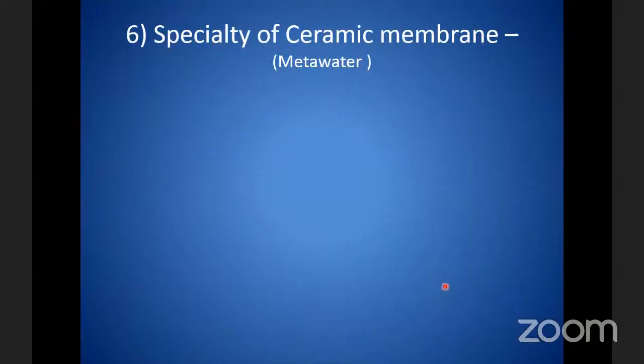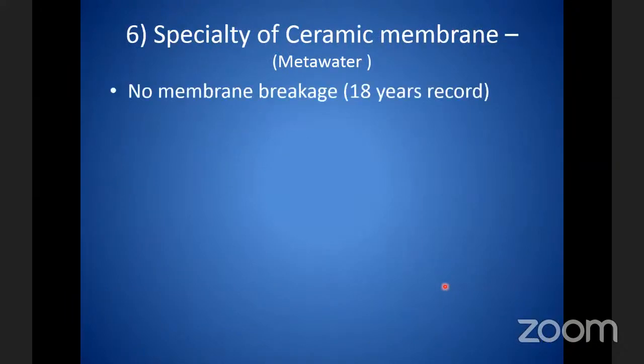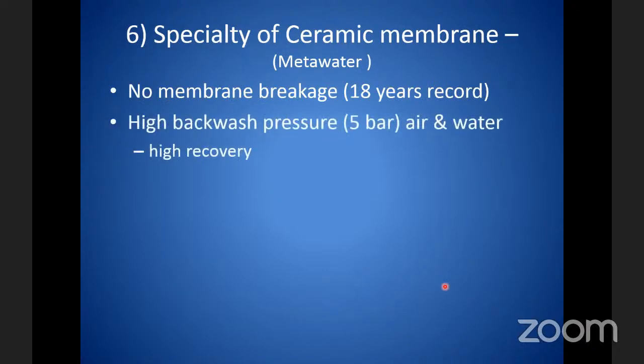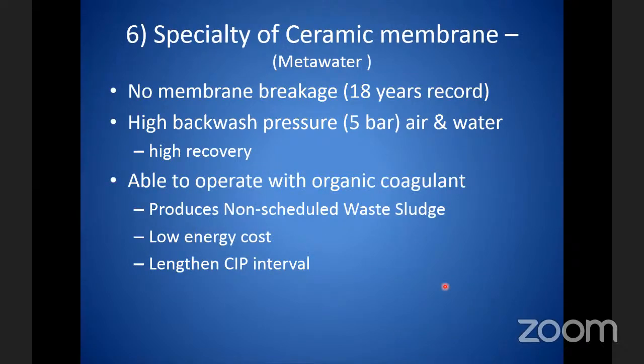The specialty of this type of ceramic membrane, Metawater, is that it has recorded no membrane breakage for 18 years. High backwash pressure can be applied, now 5 bar. Normally, polymeric membranes cannot backwash with such a high pressure. Therefore, you can have high recovery. You don't use water to push out the concentrate, you use air to push out the concentrate.